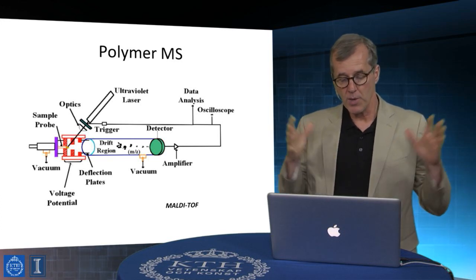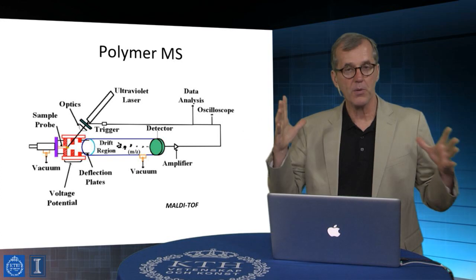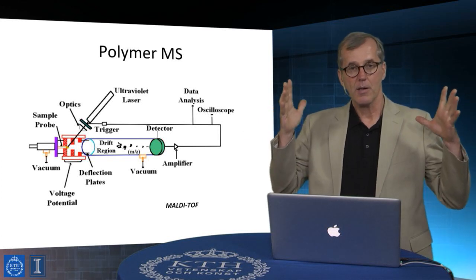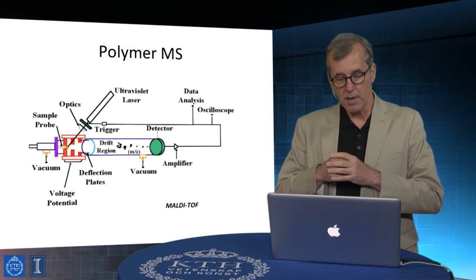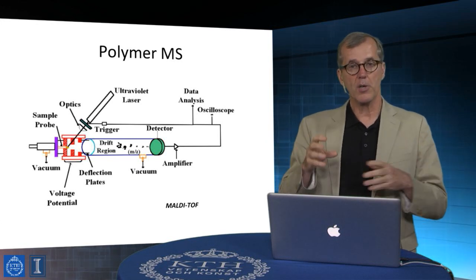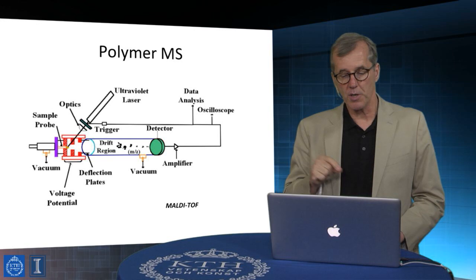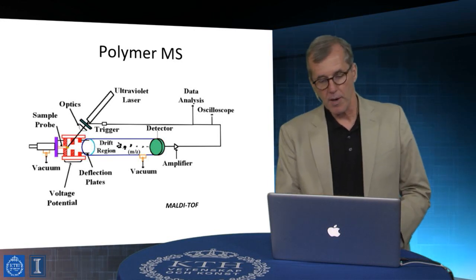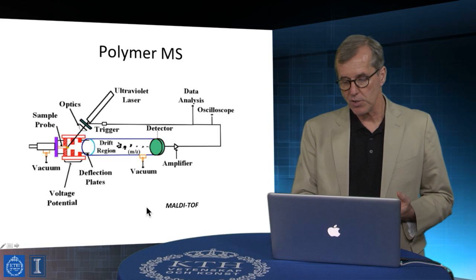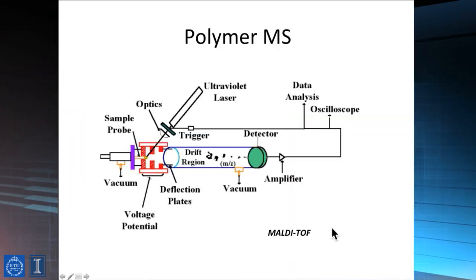And in that way, we can then use the electric field based dynamics of mass analyzers to measure charge to mass ratio in a variety of ways. So the schematic that's shown on this slide is a so-called MALDI time of flight mass analyzer, which distinguishes charge to mass ratio by the length of time it takes something to go from, basically, the front end of the mass analyzer to the detector at the back end.